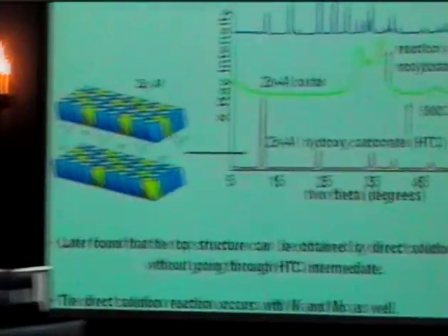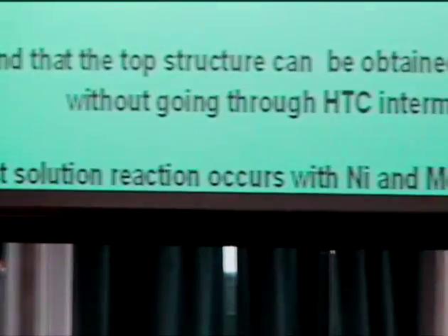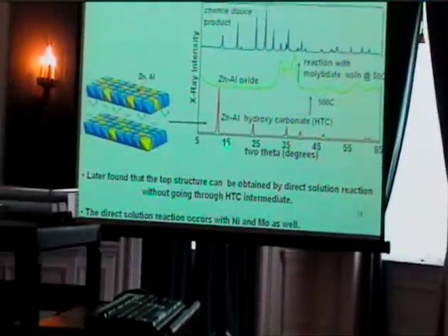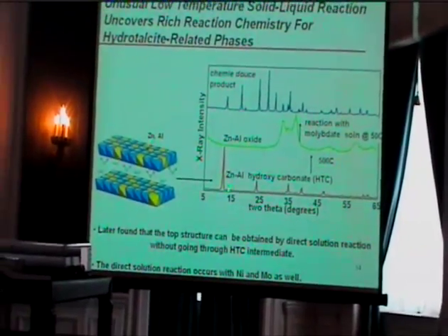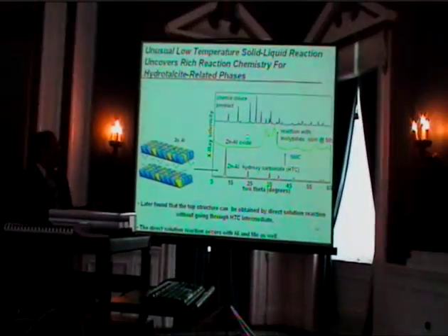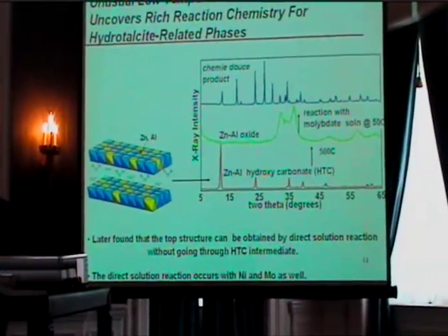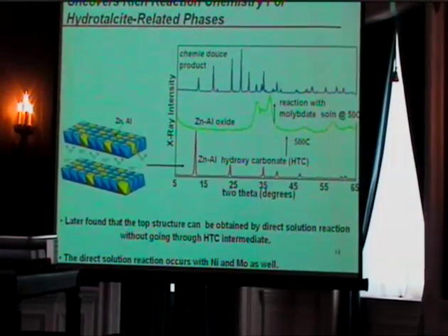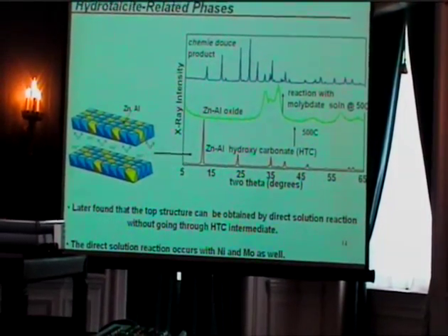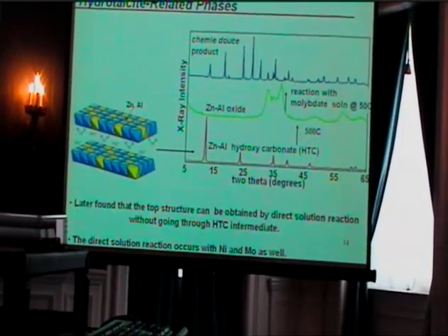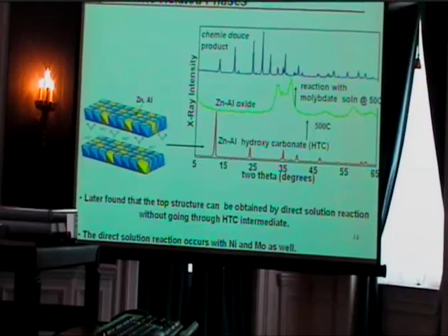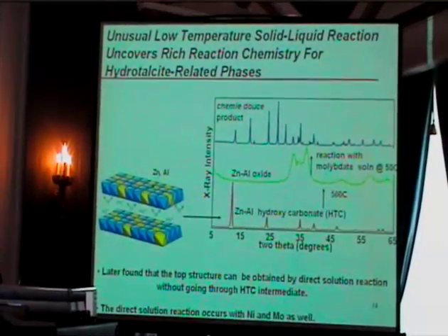Okay, as we explored further, we later found out that you can make this structure not only from the hydrotalcite, but you can actually make it from a direct solution reaction. And not only could you do it with zinc, you could do it with magnesium, you could also do it with nickel. So here we had something with nickel, here we had something with moly, here we had a new structure. Having worked for 15 years at that time in the company, having something interesting and different with nickel and moly sort of raised our attention. And the fact that we were seeing some low temperature chemistry and things going on in this metastable region sort of raised a flag in our minds.